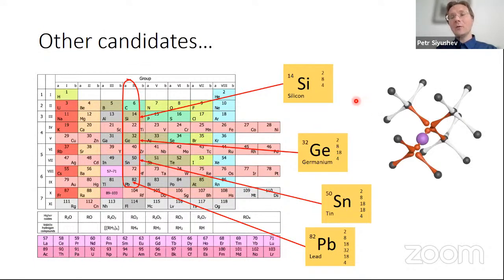And surprisingly, or maybe not surprisingly, all have a similar or basically identical physical structure, where the impurity atom is aligned along the bond between two carbon atoms, and because the atom is pushing out these two carbon atoms, it creates the so-called split vacancy configuration. And that's actually a very nice thing about these defects, because it provides this D3d symmetry. I will talk about this a little bit later.